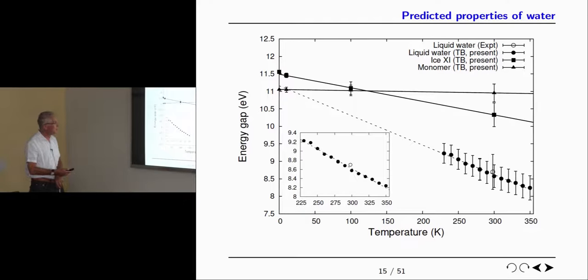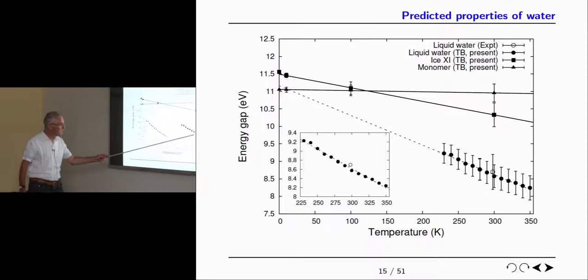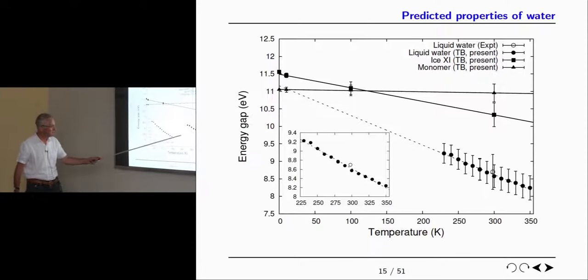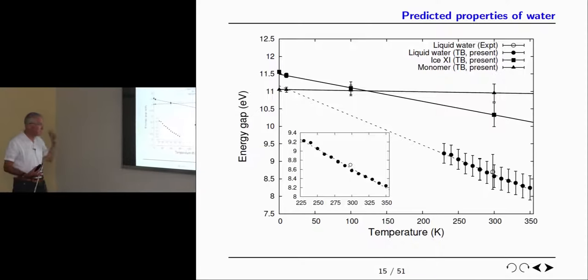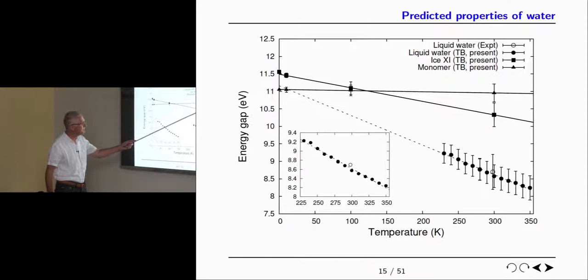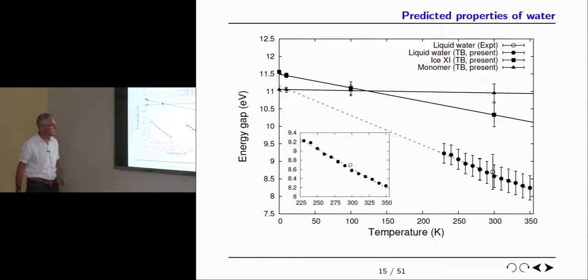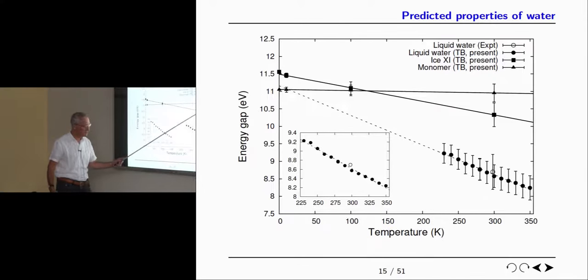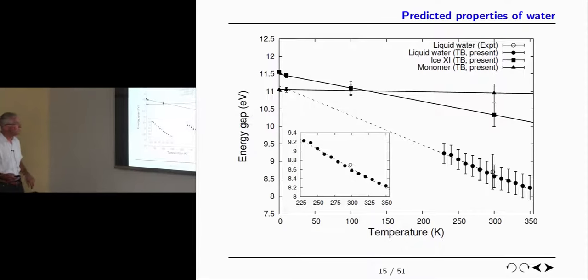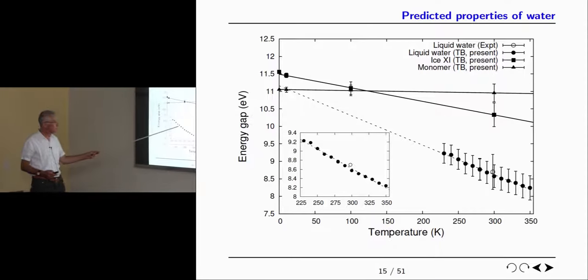This is the band gap. People don't often publish or calculate the band gap of liquid water, but we've done it here as a function of temperature. These are our data here. There's one experimental point that we could find. It's probably the coincidence is too good. And anyway, what the hell do you mean by band gap? So at any rate, it's a trend. And we have the band gap of the monomer. But the point is that the band gap of the monomer is much larger than the band gap of the liquid. That's interesting. The band gap of the liquid gets smaller with temperature, and here's the band gap of ice as a function of temperature, all calculated within our model and compared with one experimental data point.